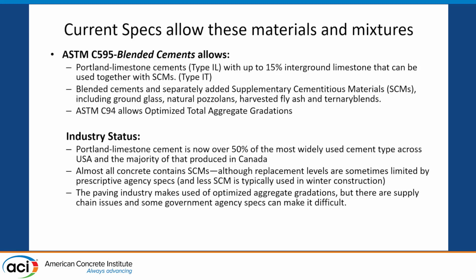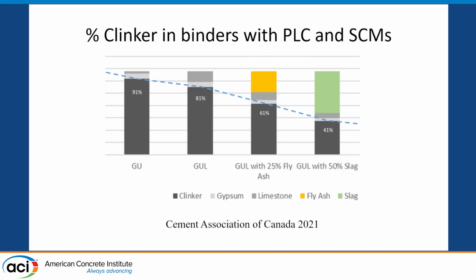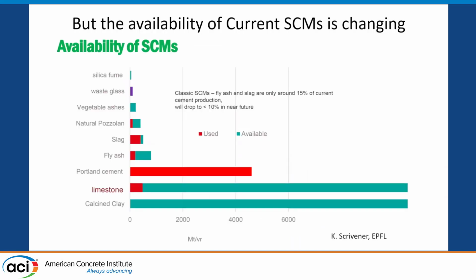All concrete contains SCMs pretty much, but like I said, some of them are restricted by prescriptive agency specifications, which are often legacy type specifications. And not many people do the aggregate optimization. So it's fairly easy. As I mentioned, this is just a cartoon from the Cement Association of Canada report. Just using a limestone cement with either a moderate amount of fly ash or slag, you can get down in the 50% reduction range. Now, Mary mentioned this earlier.